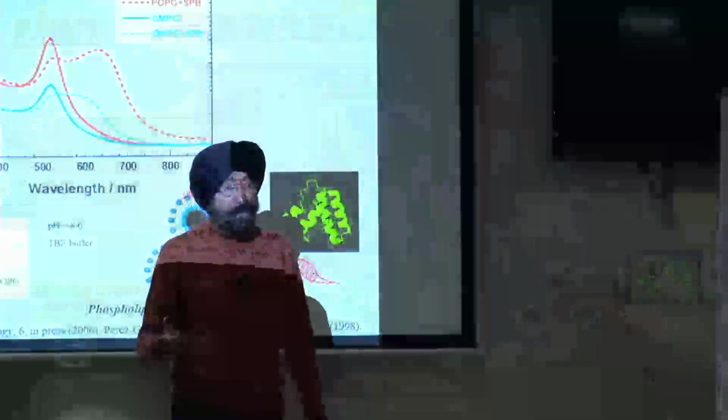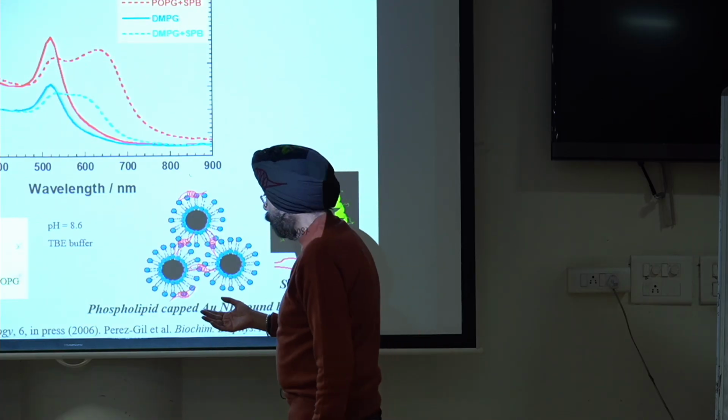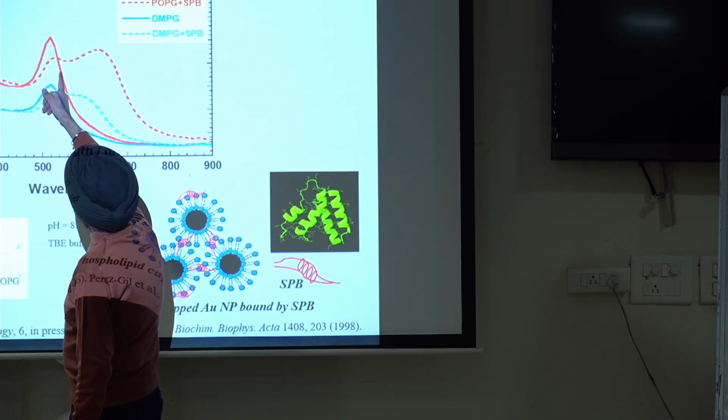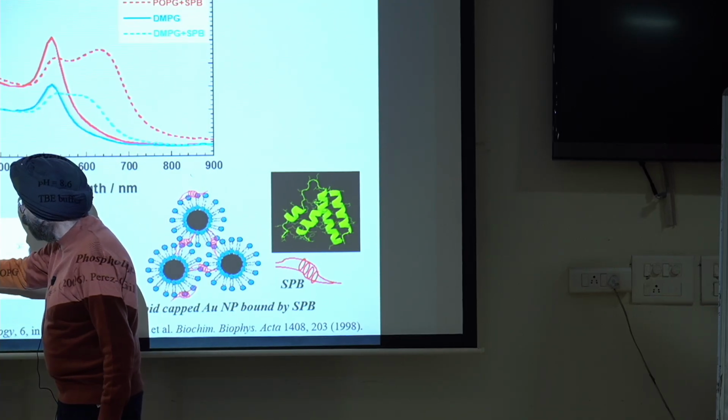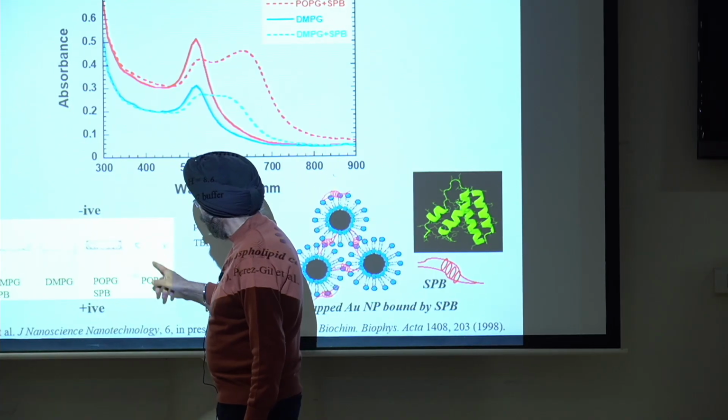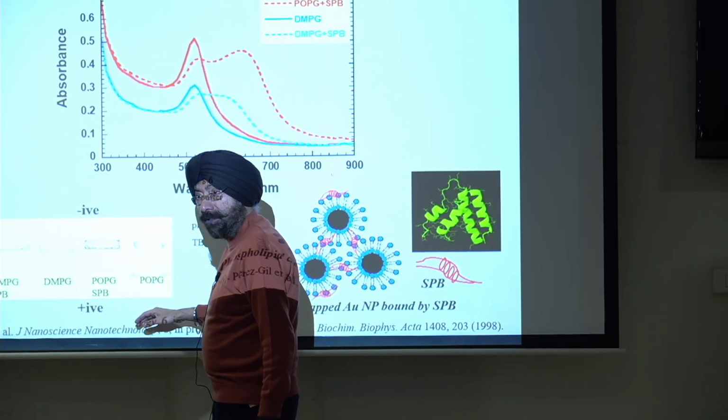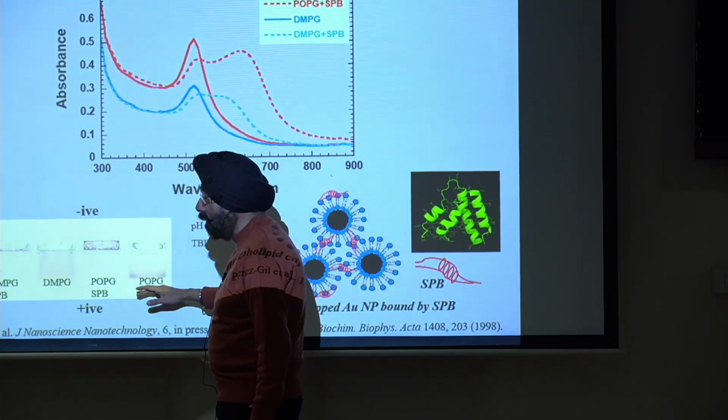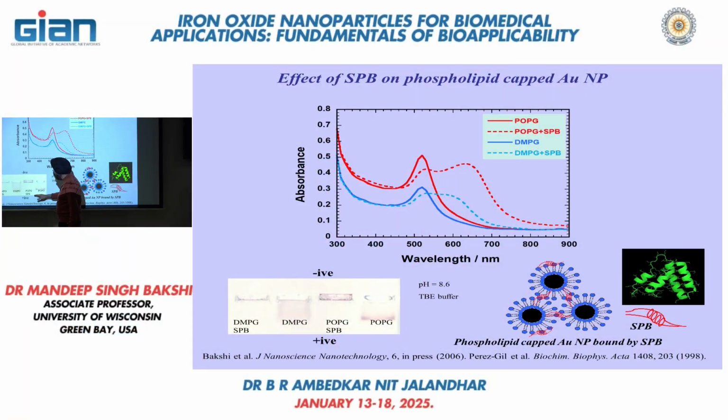It is everywhere in the biology lab. What you could do, the same sample without the surfactant protein B, if you are going to put it in the gel well here for POPG, apply the voltage, you see there is a transfer of the nanoparticles towards the positively charged electrode, because these POPG are predominantly negatively charged. So the bilayer shell that is being created on the surface of the nanoparticle is predominantly negatively charged. So it means that they are going to move towards the positively charged electrode.